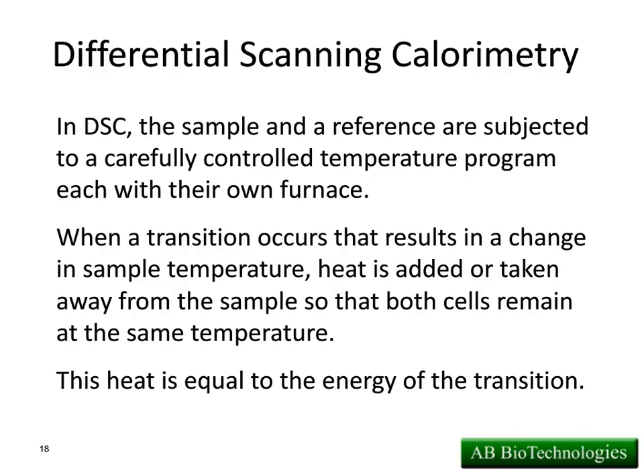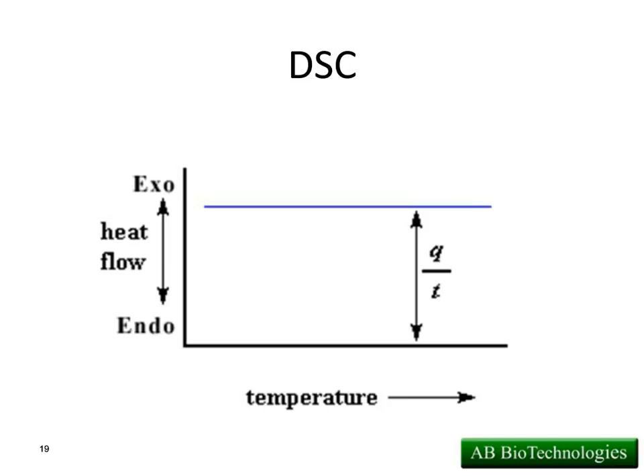So what we've also got there are two thermal benches, or ovens, essentially, or furnaces. The sample goes on one. An empty reference pan goes on the other. And we'll talk about what's going on with heat transfer. Basically, what the DSC is measuring is heat flow. It's not measuring a change in temperature between the sample and the reference. So as we increase in temperature, we're monitoring the heat flow. The way the DSC works is that the instrument wants to keep the sample and the reference pan at the same temperature.